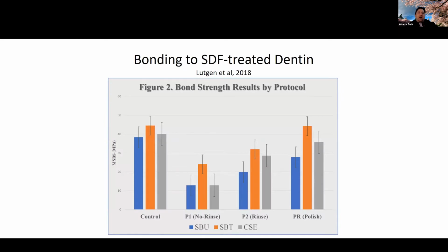So people ask a lot about bonding to SDF treated dentin. What if I have a deep caries and I go ahead and apply silver diamine fluoride, and now I want to bond to it? I just don't want to use glass ionomer for whatever reason that I have. What is the best protocol to bond to silver diamine fluoride treated dentin? And this is a study we did in 2018, published in Dental Materials again. We looked at the bond strength of two different bonding agents.